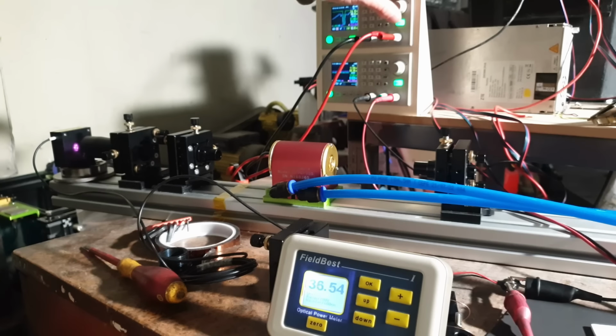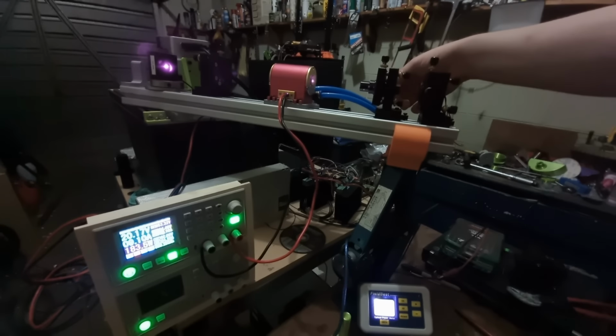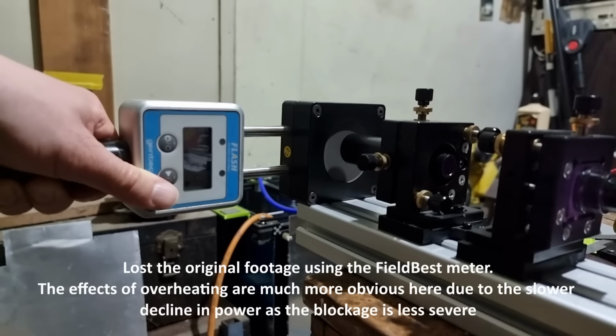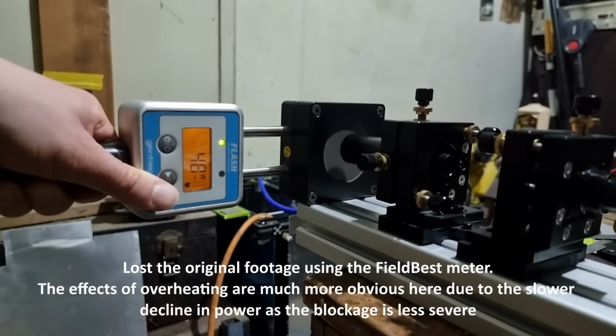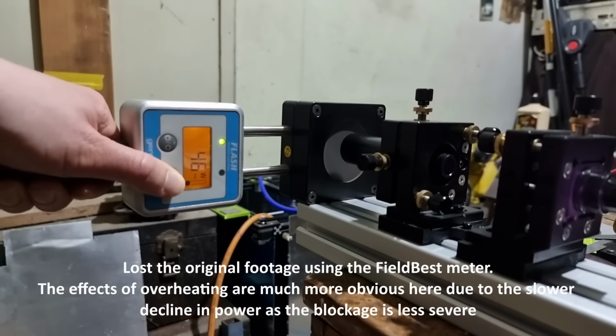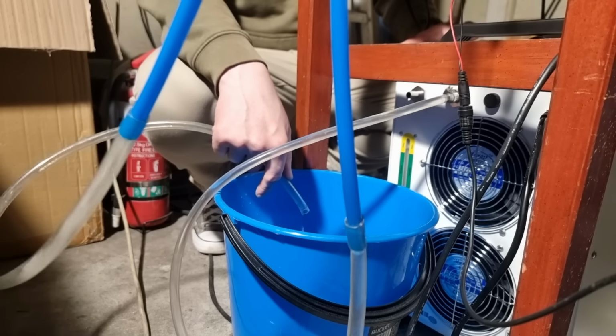Even so, this should still produce 62 watts, but with the unit plateauing at 38 watts it was evident that there was something wrong. The power meter I would use to dial in the laser is just a cheaper unit, but it gives real-time feedback which is nice to have while making subtle adjustments to the mirrors. As I would power the laser up, I would see a brief spike to around 50 watts, with the power settling to below 40 watts. Unsure of whether it was just the meter stabilising or whether it was the power rolling back due to overheating, my initial suspicion was that there was a blockage within the pump, and I would test the flow, finding it to be above average. I would then spend more time than I would like to admit second-guessing myself, wondering how selective I actually needed to be with the alignment.